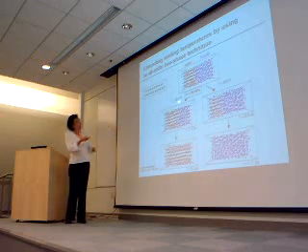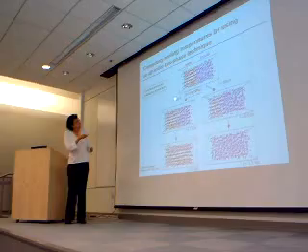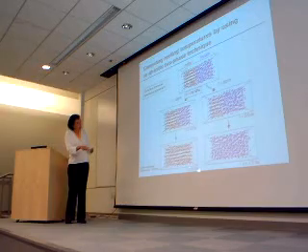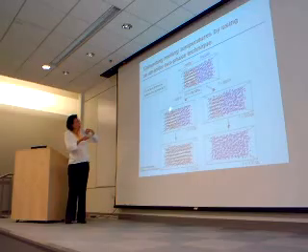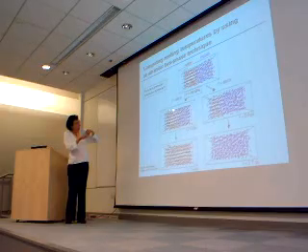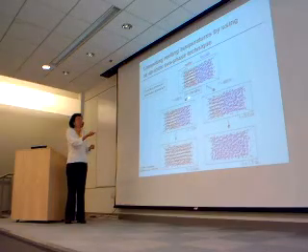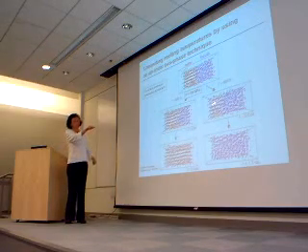You look, and for example, here you simulate at a certain temperature, 800 K. You simulate for a certain time. This is a very short time. This was a system which was actually quite fast to simulate. And you see, for this system, at this fixed pressure, at this temperature, the phase that wins is the solid. Then you go to another temperature, same pressure, and you see the phase.